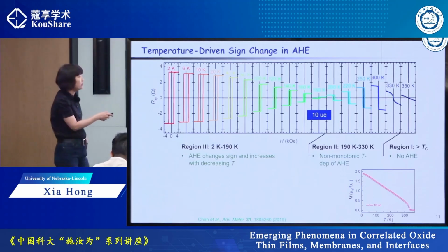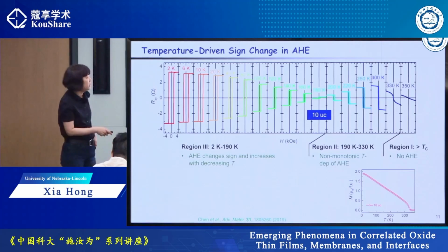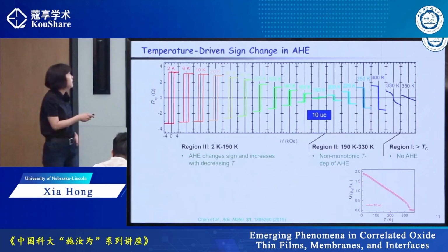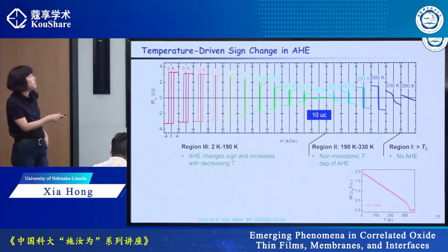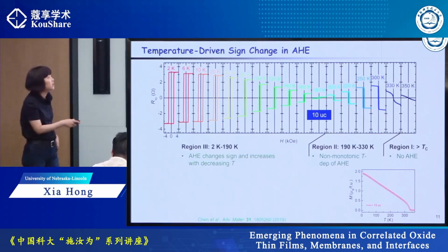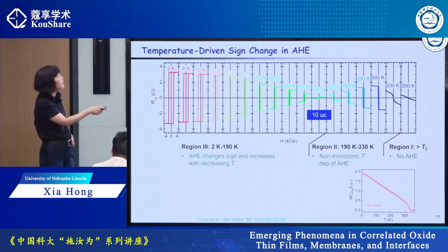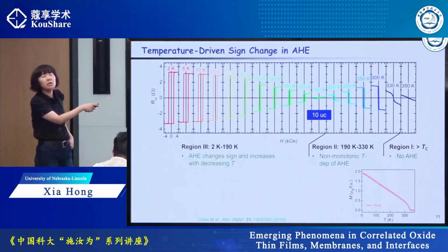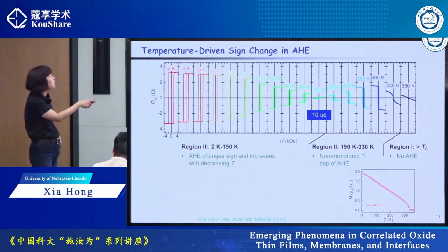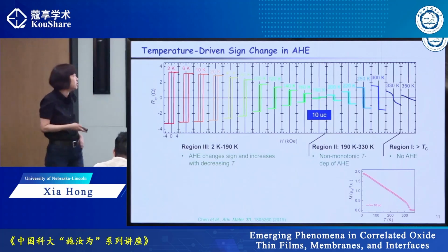But 190 Kelvin, what's so critical about it? Because if you look at the magnetization as a function of temperature, nothing happened there. When it re-emerges, you can see that it actually changes the sign. So above 190 K is basically counterclockwise hysteresis, but below it is a clockwise hysteresis. So what's going on?